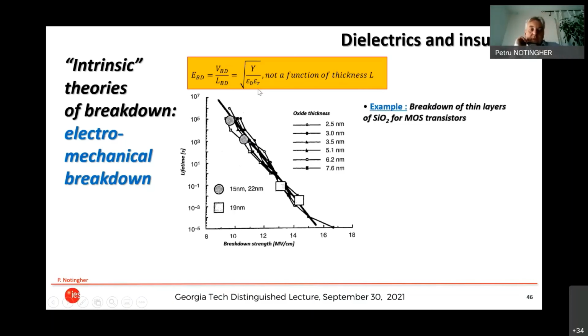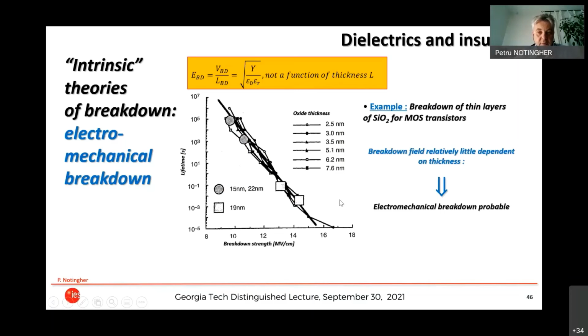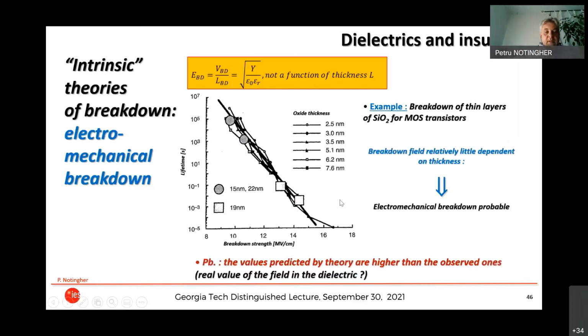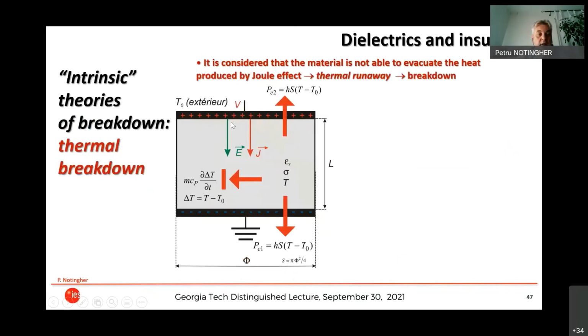So we have observed such behavior in thin layers of silicon dioxide. You see that whatever the thickness here, the breakdown strength and the lifetime are the same. So this is an indication of an electromechanical breakdown. The problem is that the values which are predicted by the theory are higher than the observed ones, maybe because the real field in the dielectric, the real value, is not V over L. Another theory which works well on thick materials is the thermal breakdown theory.